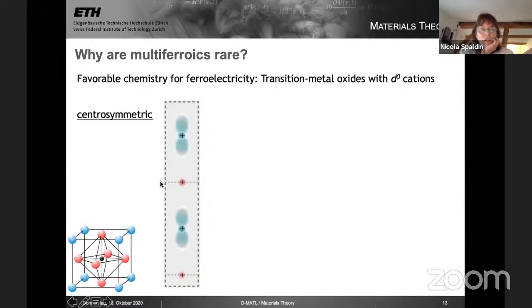And here's a cartoon of why. A prototypical ferroelectric would be, say, barium titanate. The transition metal is titanium 4+, which doesn't have any d electrons. It's given up its 3d electrons. It's octahedrally surrounded by oxygen 2- ions, which have filled p shells. And at the corners are barium 2+ ions, which are closed shell. They're not doing anything with the chemistry. Here it's in its centrosymmetric structure, the structure at high temperature, so it doesn't have an electric dipole. It's in the paraelectric state.